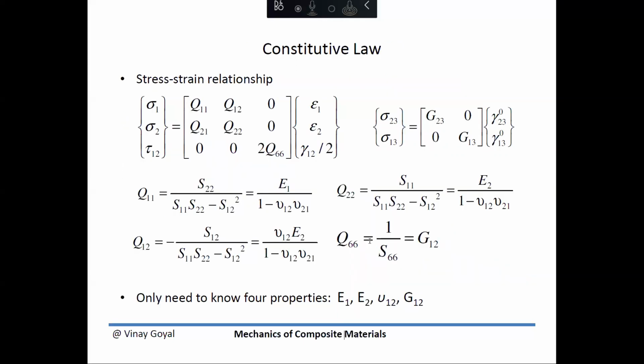I will now look at the constitutive law that we have previously described. If you recall, the stress in the local material orientation system can be related to the strains through this constitutive law, where Q11, Q12, and Q22 are given here, and E11, E22, NU12, and G12 can be found through ASTM standards. We also have now two stresses that relate to two transverse shear strains that used to be zero, and are now existent in this theory. We have the transverse shear moduli, which can also be calculated with the Iosipescu test, as was previously discussed. So now we have, in classical plate theory, we did not have these two extra stresses being discussed.